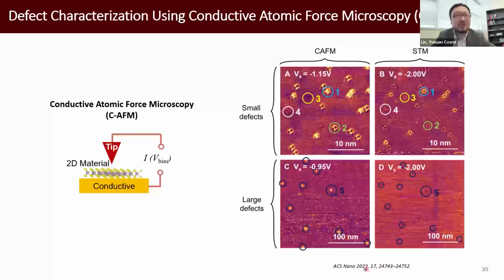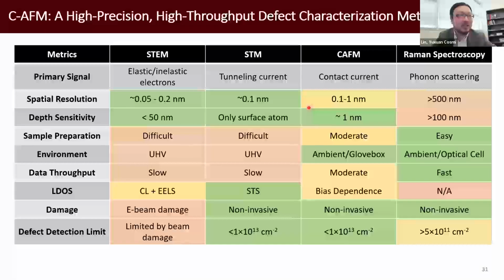This is from a recent study. The first column are the conductive AFM results. All those features correspond to point defects in TMDs. The right-hand side are the correlated measurements with scanning tunneling microscopy. You can see a very clear one-to-one mapping. Even those slight, tiny features give you a correlation. But conductive AFM is more accessible. The instrument itself is cheaper and relatively faster compared to other approaches.